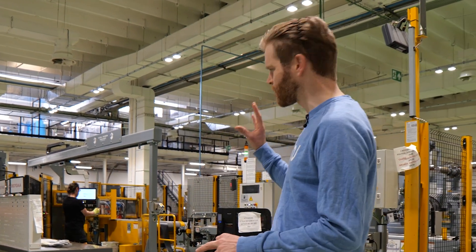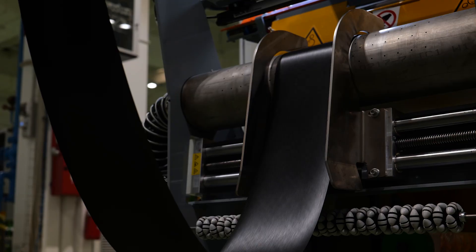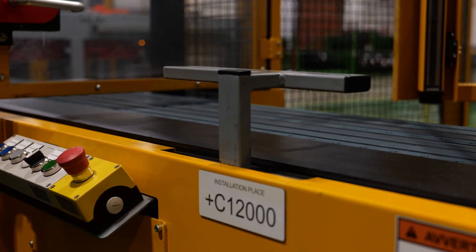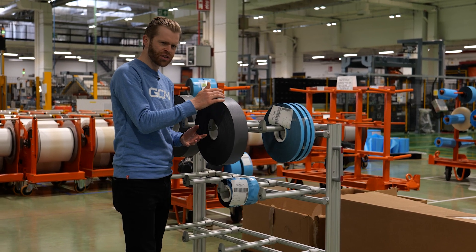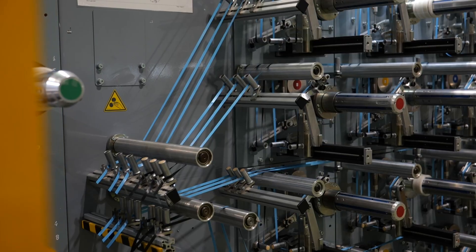The first thing they do is get the material that's going to make up the parts of the tires and cut it to length. This is done on the CNC profilers behind me. It's important because it's more accurate than a human, but also it minimizes human contact with the material — important because this material hasn't been vulcanized yet, making it really delicate, thin, and very sticky. Other bits being cut to length include the puncture breaker, the innerliner used in tubeless tires to help keep them airtight, and a thinner layer for the bead to reinforce and protect it. All these bits will come together later.